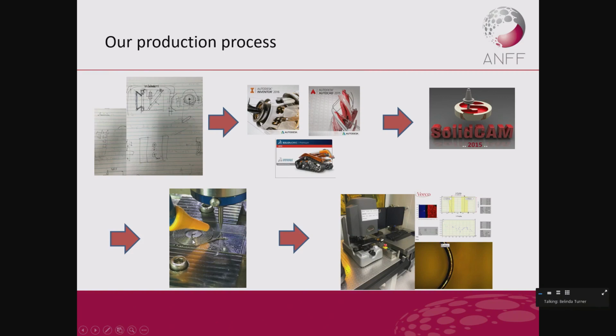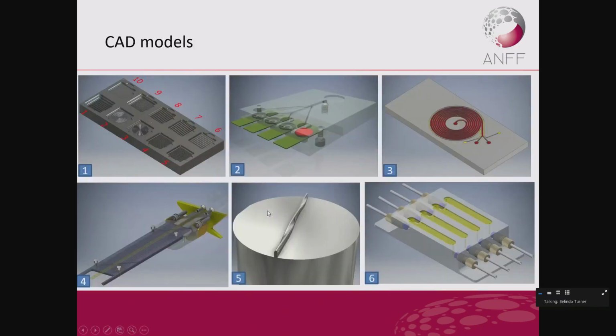In this case, it was a spiral separation mould to extract tumour cells from your blood. And as we go through this process, we'll be constantly inspecting it. This was a Veeco optical profilometer, so we can inspect it to within a micron. And the inspection really is the thing we couldn't live without, because if we don't know what we're making, we haven't got a chance of applying offsets or knowing where we are. So it's a really important factor in our process.